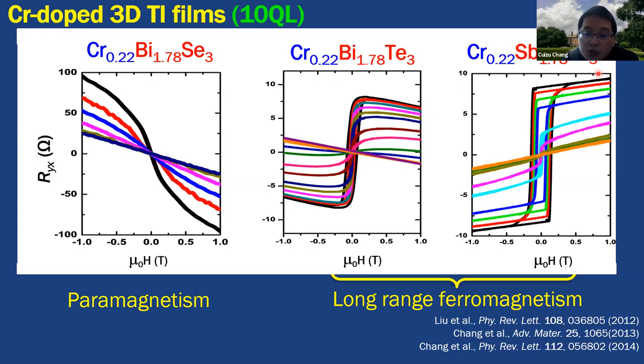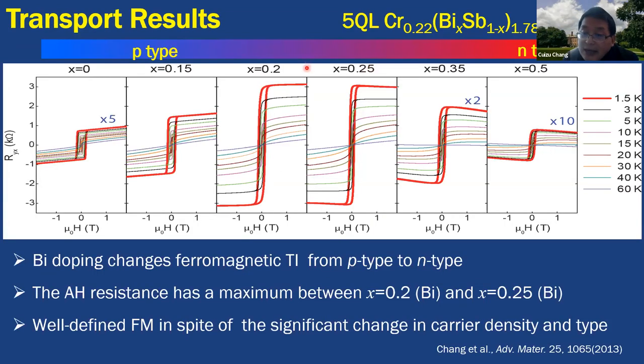So in order to tune the chemical potential close to the magnetic exchange gap, we decided to mix this chromium-doped bismuth telluride and chromium-doped antimony telluride to form the four-element material, chromium-doped bismuth antimony telluride, in order to tune the chemical potential into the magnetic exchange gap. And let's take a look.